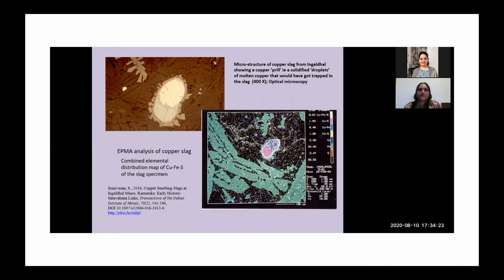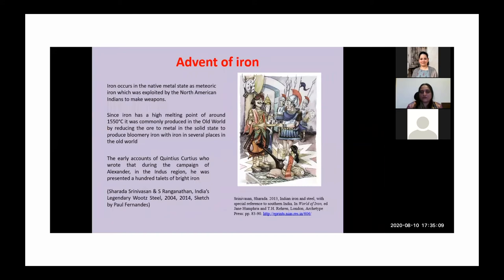So in this case, you can see it's quite dramatic, because you see that the copper is concentrating, of course, in that metal prill, which looks very light colored, as you can see. And the pink ring around it corresponds to the sulfur rich region. So it is really separated from the sulfide and has got reduced in that sense. And then all around it, you see these iron rich laths, which is the fayalite slag. And that is also quite interesting, because sometimes the traces of elements which separate into the copper are also useful to us, as I'll be talking a bit tomorrow, when it comes to maybe attempting correlations between artifacts and ores and such like.